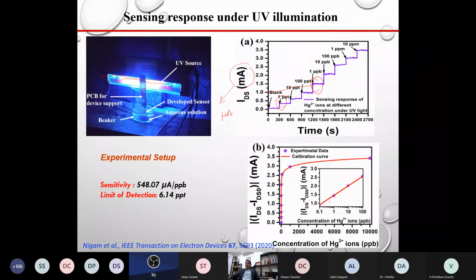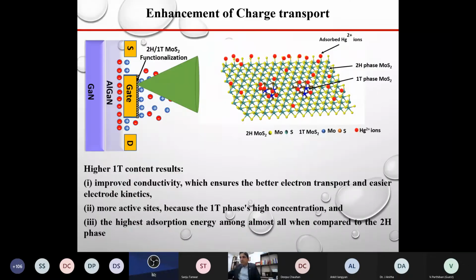Again, here you can see the linear detection range is almost similar. And if we see the sensing response, the sensitivity is around 850 times higher than without UV. So just by mounting this sensor near the UV lamp, because water purifiers have a UV lamp, we can improve the sensitivity around 850 times higher than without UV.